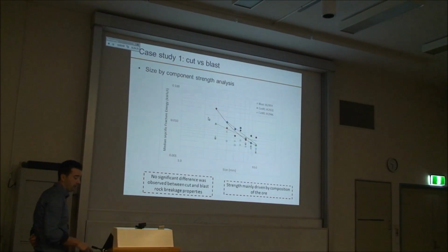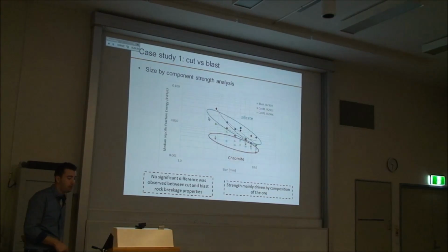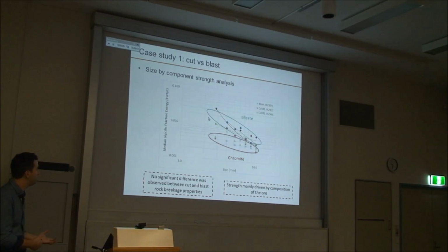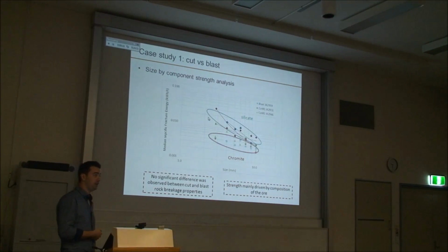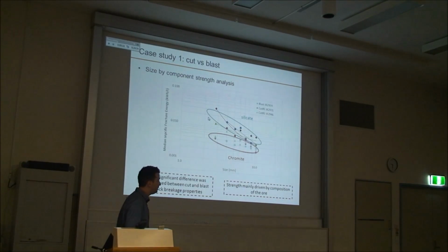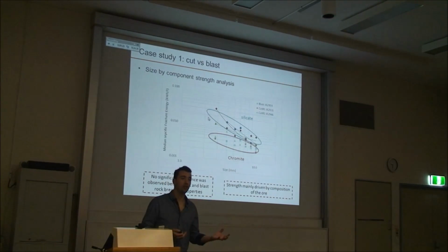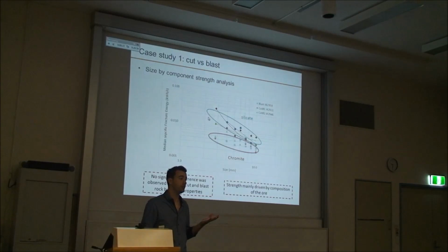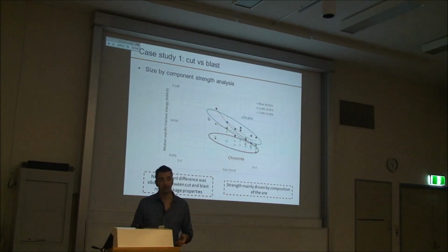But what we also found is that when you plot the chromite and the silicate together, you find that they have different strength with the size relationship. And that the actual strength of the ore is driven by the composition. What we later found out, and I'm not going to go into details here, is that the blast and the cut rock had different proportions of the components. So the one that had more chromite was actually softer. But it's not because of the cutting mechanism or the blasting mechanism, but just because of the composition.